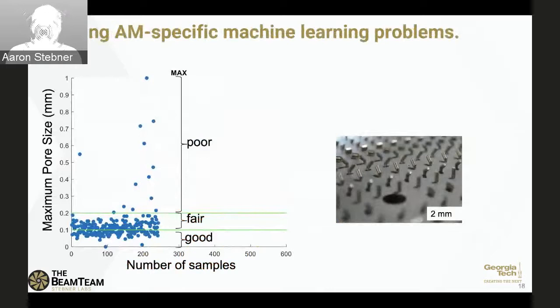And the answer, right, came out that it was repeatable. We always had the maximum defect in the same part. You see that one part there having like a 1 millimeter size pore and a couple having 700 microns pore. Those were always problem points in the build space and build orientation map, but they were statistical outliers. They weren't good for machine learning, it ended up, right? Because even though they were deterministic and repeatable, statistically, they don't correlate to the main statistical distribution of the data.